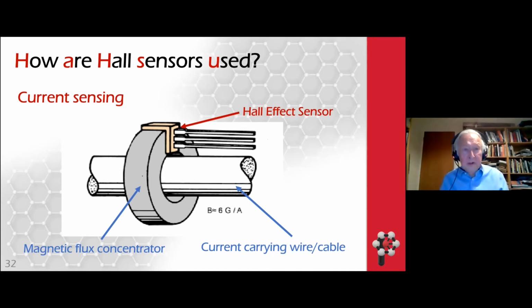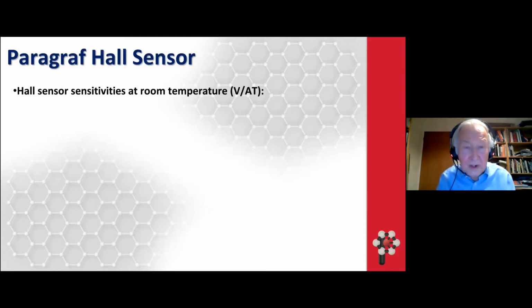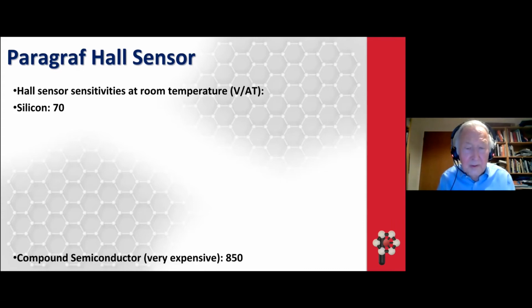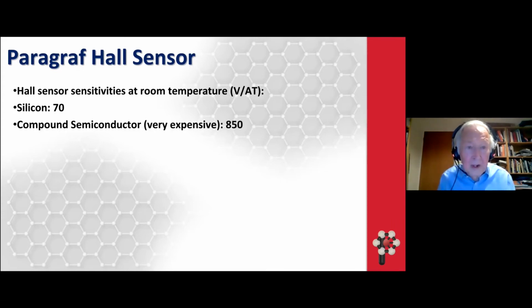So let's look at the performance of the graphene sensor. So does this graphene sensor really live up to its reputation of being a wonder material? So these are sensitivities of different Hall sensors at room temperature, and the unit that sensitivity is measured in is volts per amp Tesla. A silicon Hall sensor has a typical sensitivity of 70 volts per amp Tesla. Compound semiconductor, so this is a quantum well of gallium arsenide, that's 850, significantly better than silicon. The Bosch graphene flakes that they were talking about in the press release, that was 1,250 if you look at their paper, but it's not manufacturable. The Paragraf Hall sensor is greater than 2000. So it's 30 times better than a silicon Hall sensor.